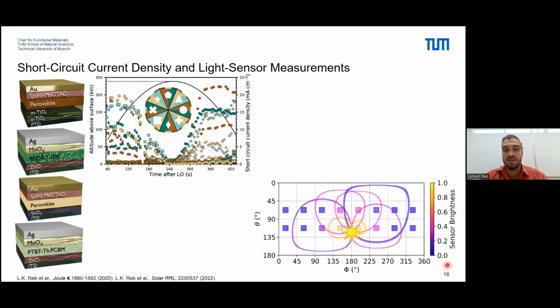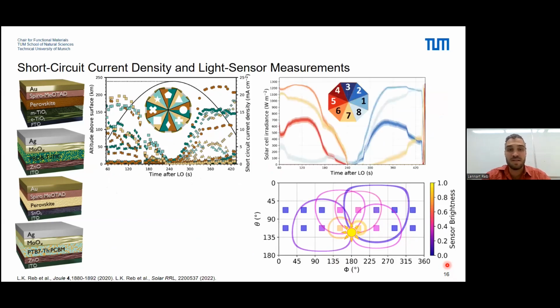By using Bayesian optimization and also Markov chain Monte Carlo modeling, we could consistently sample the posterior probability distribution of the solar irradiance onto every single solar cell during the entire main measurement time of the flight that you can see here on the top right. Just as a validity check, for example, this number 1 that shows the highest solar irradiance converts here to the circle segment that also shows the highest short circuit current densities.